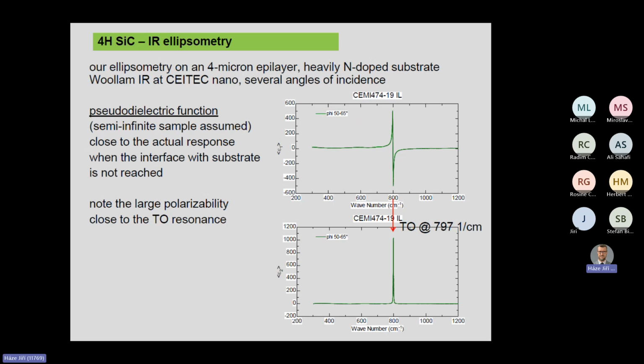So we have also ellipsometric data, which are very good because at each photon energy they provide two real numbers. This is what we need for the optical responses. The basic picture of the ellipsometric results is the pseudo-dielectric functions. We just assume we have a half-infinite ideal material below the surface, and we plot the real and imaginary part of the dielectric function, the complex permittivity.